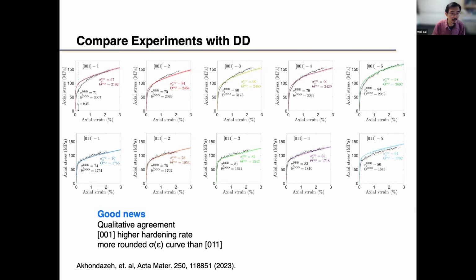The good news, okay, let me say the good news first, is that you can see that there is actually pretty good qualitative agreement in the shape of the stress strain curves, okay? And not only that, you can even see that in the 001 orientation, the stress strain curve is more rounded, and then the 011 is more corner. Even that is captured. So we're quite encouraged by that.